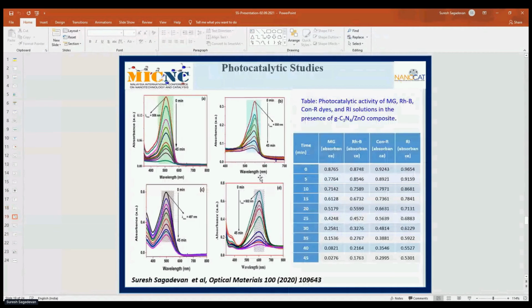After that, we studied the photocatalytic activities only for the composite sample, because further study is going on. We performed the photocatalytic activity of the composite sample using 4 different organic dyes: malachite green, rhodamine B, Congo red, and red ink. In the presence of UV light radiation, you can clearly see from the figure that the time interval for all dyes is 0 to 45 minutes. Significant photocatalytic activity was observed only for this composite. You can see from the table the photocatalytic activity of malachite green, rhodamine B, Congo red, and red ink solutions.